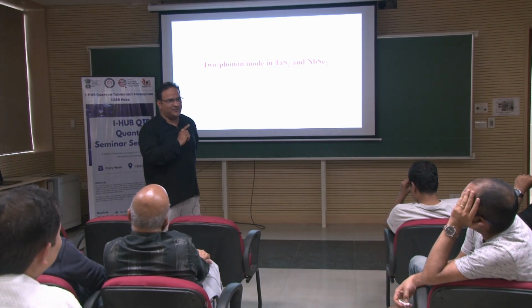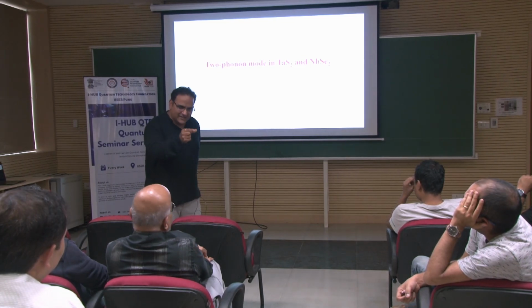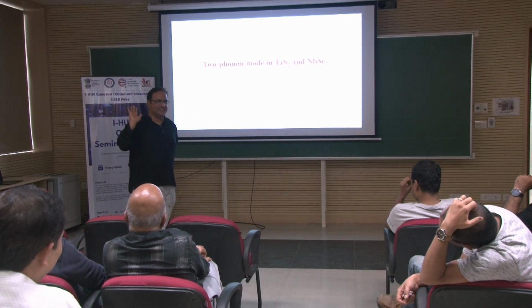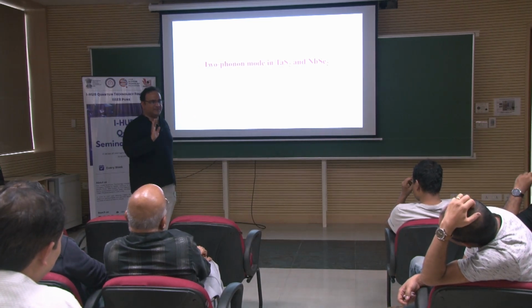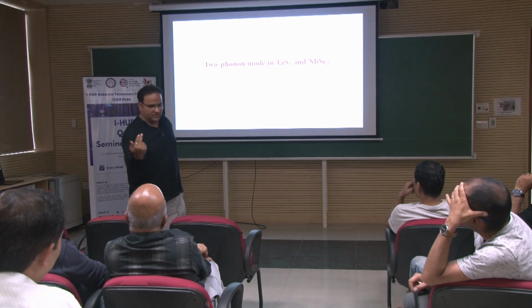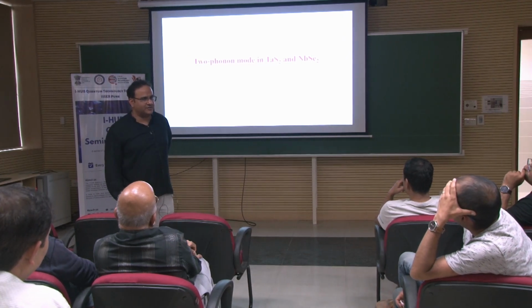The problem is the experimental requirement of neutron scattering. They need a 5 centimeter long sample, 5 centimeter minimum diameter, and I am sorry, that is not a single crystal for me, at least in these samples. And we have done a measurement with a 1 micron spot size, total lateral dimension maybe 10 micron or something. It's just the thickness is varying.